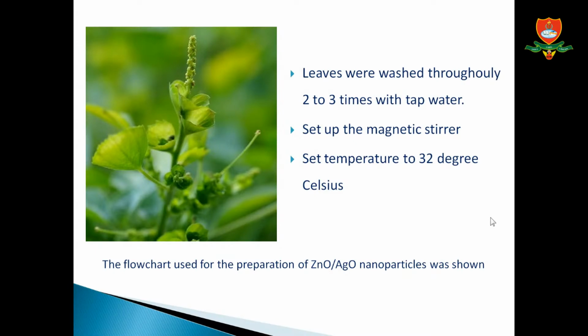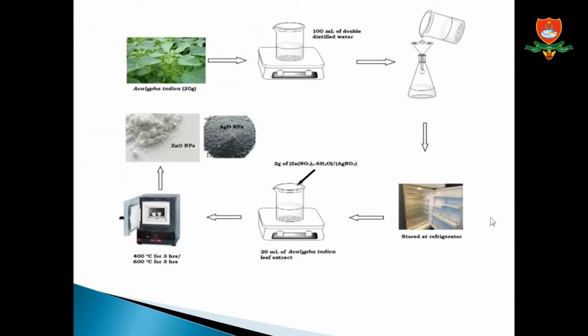The flowchart used for the preparation of zinc oxide and silver oxide nanoparticles is shown. The leaves were washed thoroughly with tap water and sterilized with double distilled water. Then the sample was allowed to dry at room temperature, 32 degrees Celsius. And 20 grams of leaves were boiled with 100 ml of distilled water, during which a dark yellow colored solution